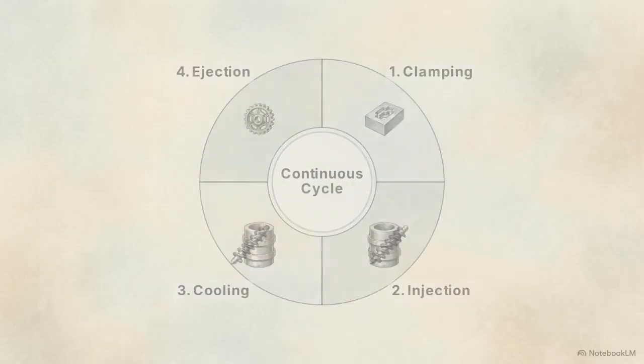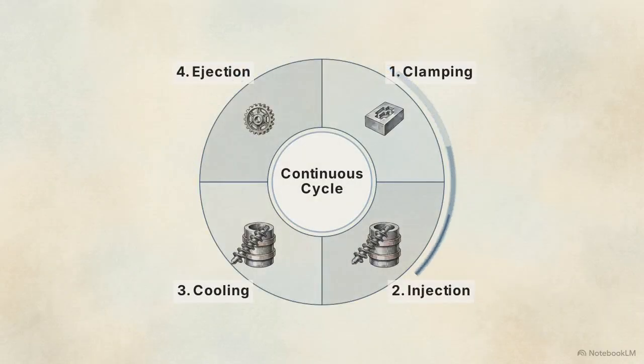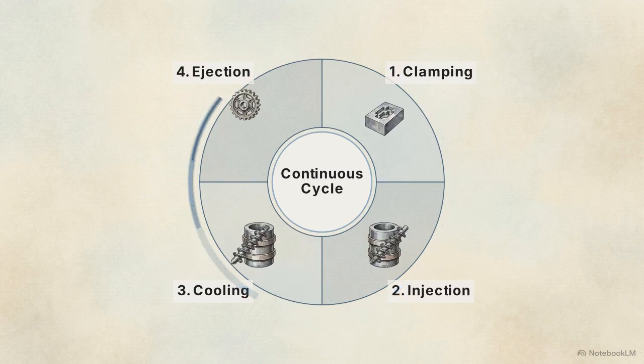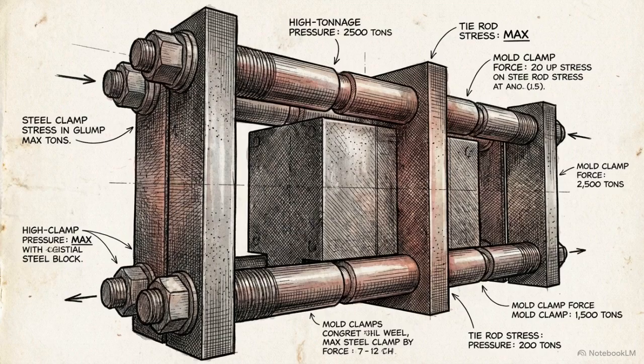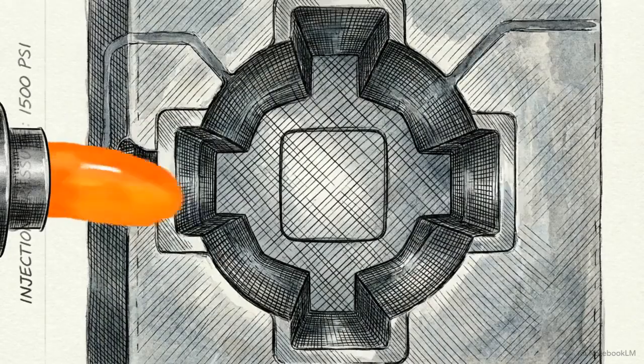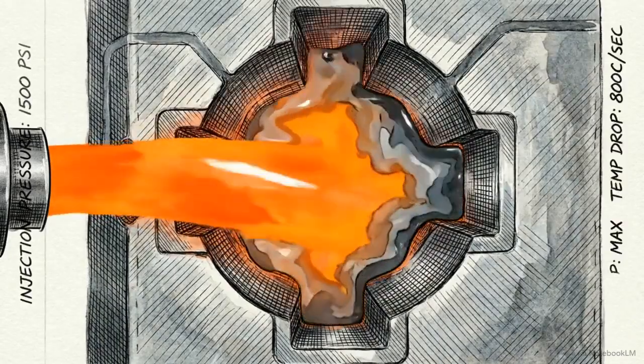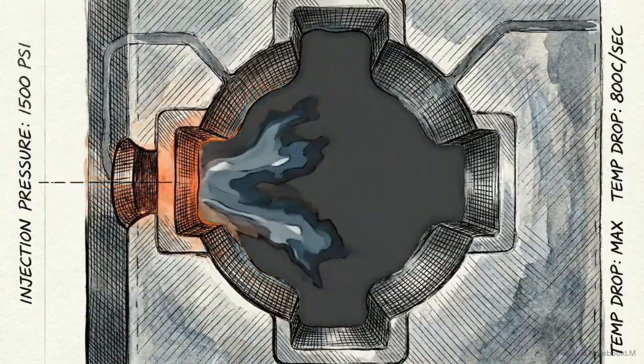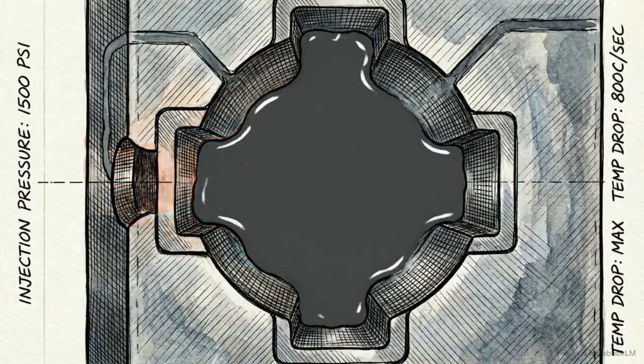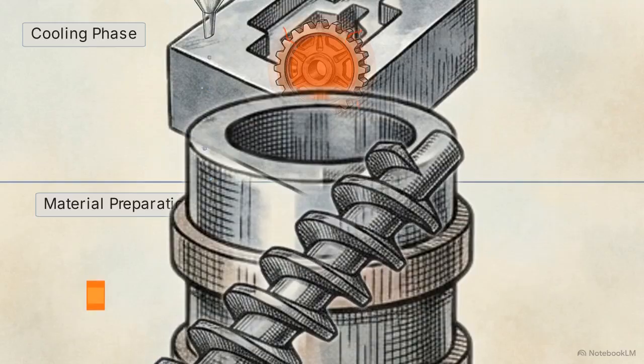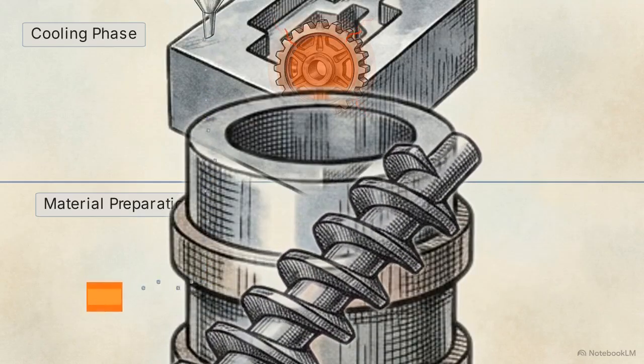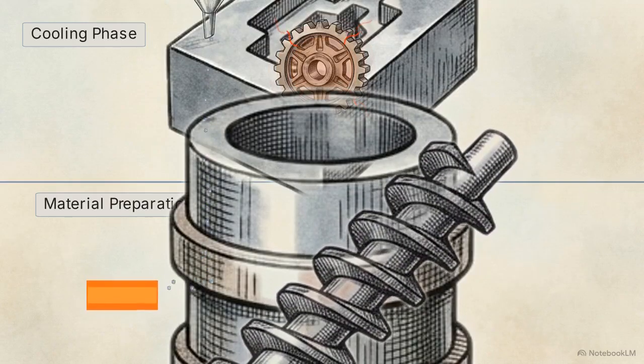The entire injection molding process is executed in a continuous 4-step cycle, where maximum efficiency is achieved by tightly overlapping these operations. In step 1, the movable platen actuates, and the mold is closed and locked under high tonnage. Step 2 is injection. A shot of melt is forced under pressure into the cold mold cavity, freezing instantly upon hitting the steel. Step 3 overlaps with the cooling phase. Crucially, while the part cools inside the mold, the reciprocating screw begins rotating and retracting, actively preparing a fresh batch of polymer for the next shot.